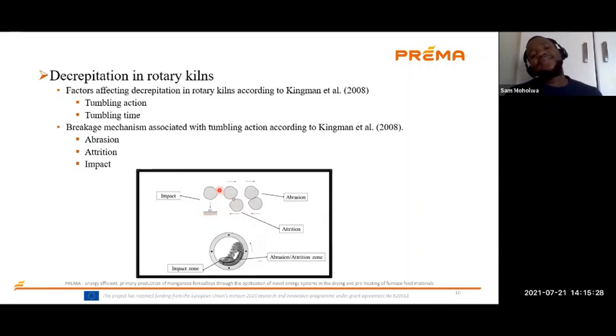And finally, we have the impact mechanism. This impact mechanism is mainly due to the collision of the particles with each other, or the collision of particles with the wall of the rotary kiln. Here you can see that we have zones where these mechanisms usually occur. Here is the impact zone where these particles are colliding with each other. Here we have the attrition and abrasion zone where these particles are rubbing with the walls of the kiln and are rubbing against each other.